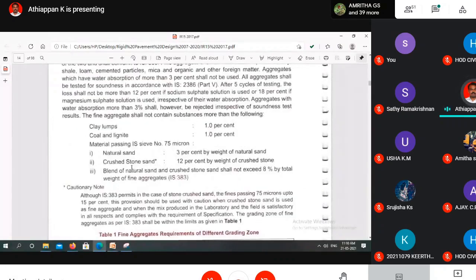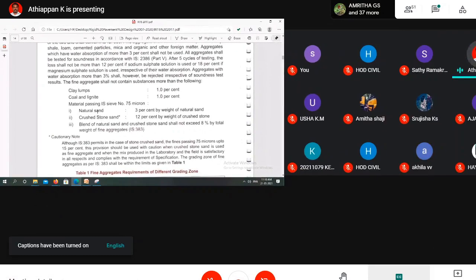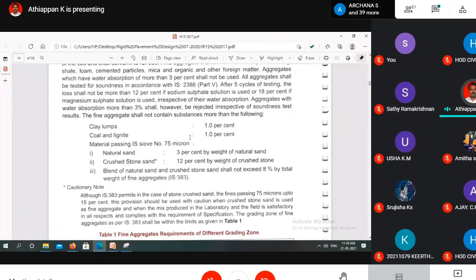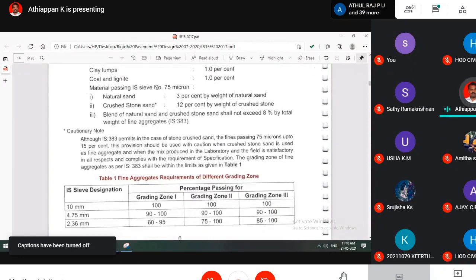Okay, so for the construction of the concrete, clay lumps should be less than 1%. Coal and lignite should be less than 1%. Okay, so this is the case. The material passing the 75 micron sieve, in the natural sand, should not be greater than 3%, whereas in case of crushed stone we are using, it should not be greater than 12%. Okay, so if you are using the blended material, then it should not exceed 8%.